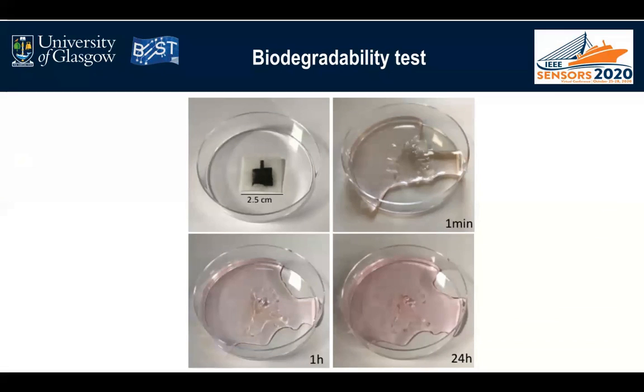So due to fast solubility of magnesium electrode, we think it's good to use some polymer with tunable degradation rate to package the device, especially for in vivo application. And in this case, biodegradable polymers such as PGS are ideal for packaging as they have a tunable degradation rate. And then the sensor functional lifetime would depend on the degradation rate of the encapsulation layer. In addition, using a thicker layer of magnesium or magnesium alloys is another way to control dissolution properties of electrodes.